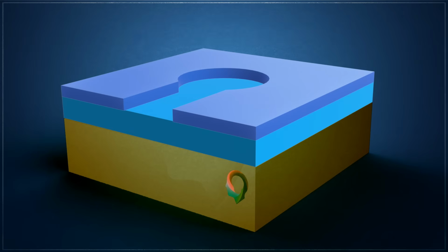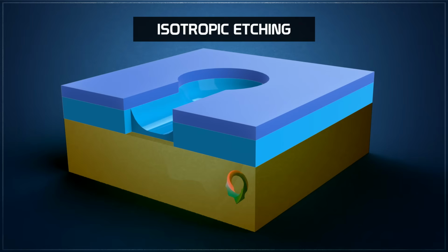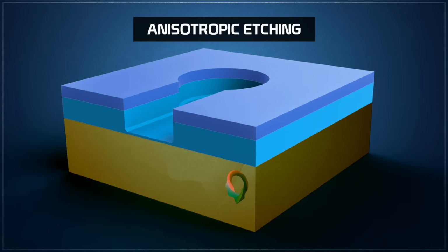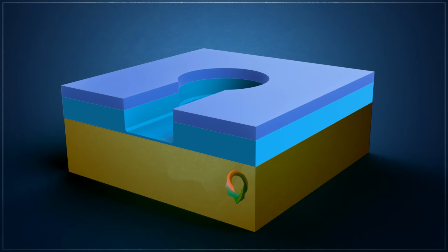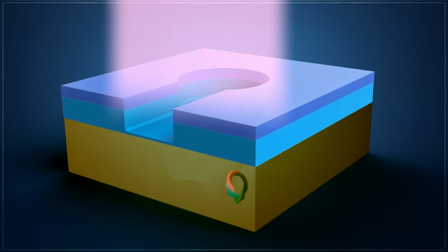In bulk micromachining, the substrate is removed in a manner similar to traditional integrated circuit techniques. An oxide mask is created, and the exposed substrate is etched away. The pattern of the etching is determined by the type of etchant. Isotropic etchants remove material equally in all directions, while anisotropic etchants are limited by the geometry of the structure to be etched. Anisotropic etchants usually etch faster in a preferred direction. The etch resistance of the substrate can also be controlled by selectively bombarding it with atoms of boron in intermediate steps using traditional photolithographic techniques.